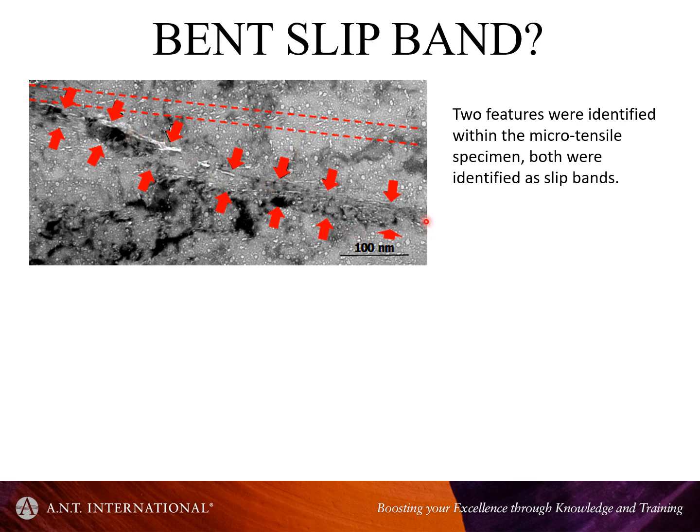So crystallographically, in my experience, when they don't share the same plane and you're talking about the same mechanism, one of them is wrong. And the very fact that it's bent is a good indication that no, this is a cluster of platelets, and it has a certain inhomogeneity, and naturally it's going to fail there ultimately.